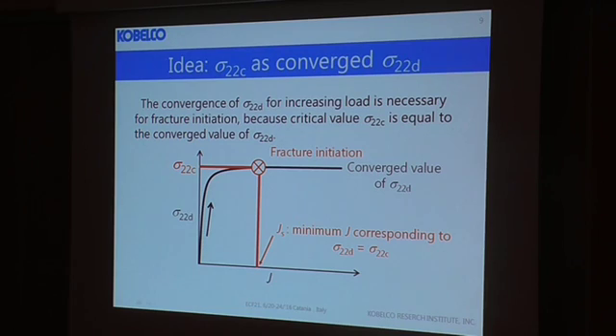Thus, we reached the idea that convergence of σ2D for increasing load is necessary for fracture initiation because the critical value σ22c is equal to the converged value of σ2D. If so, σ2D can be calculated by EPFEA with a given stress strain curve without a conducting fracture toughness test. Thus, we thought that the JC of a specimen with residual stress might be predicted without JC data with applied residual stress.